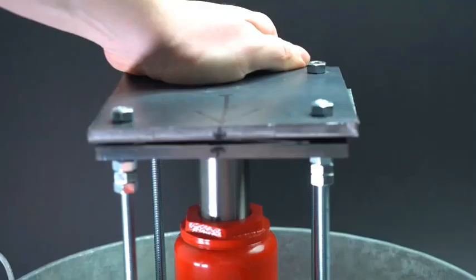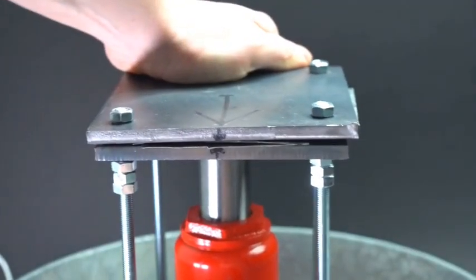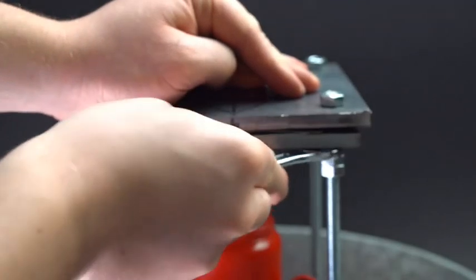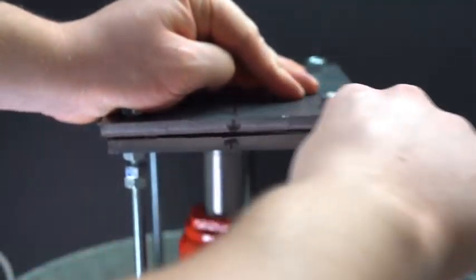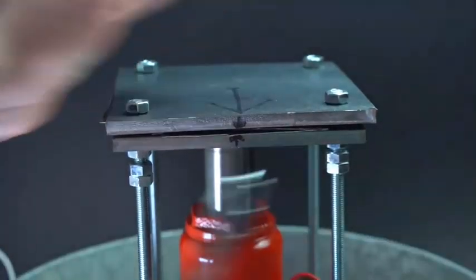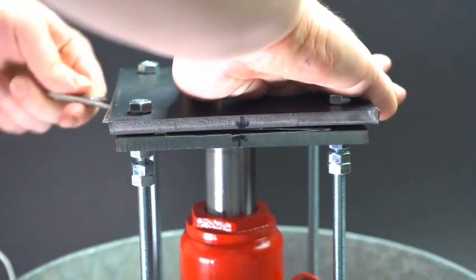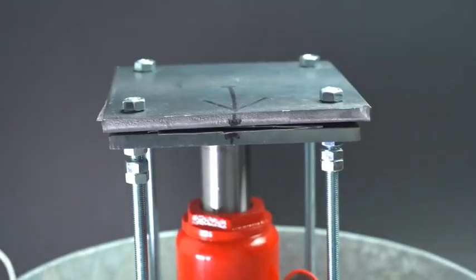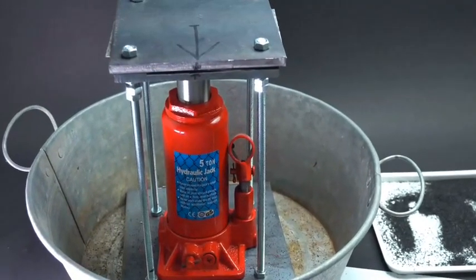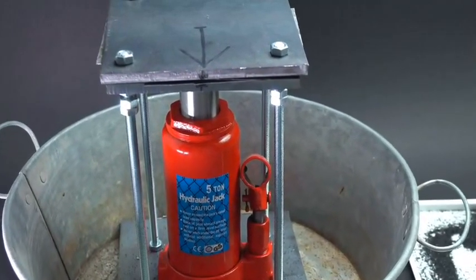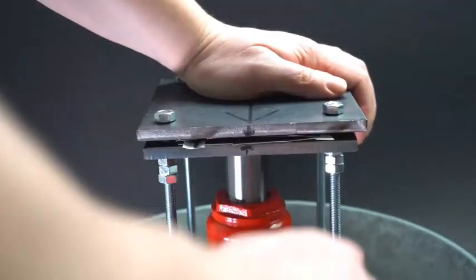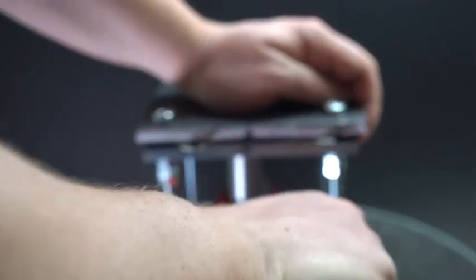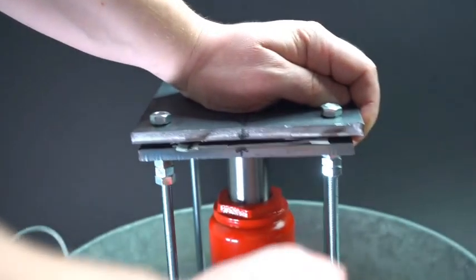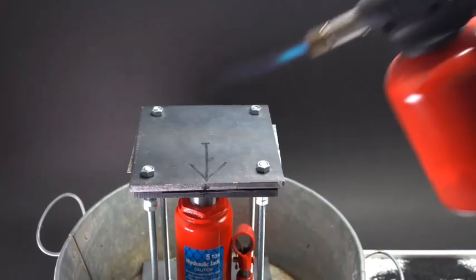Now I am securing the upper plate with nuts and start pressing the carbon cathodes as hard as I can. Then I'll tighten them with the lower nuts. When the applied pressure is high enough, the carbon will stick to the steel mesh much better. This in turn will decrease resistance and increase overall efficiency of the battery. Basically, cathodes can be left like this for 12 hours, until the epoxy adhesive hardens completely.